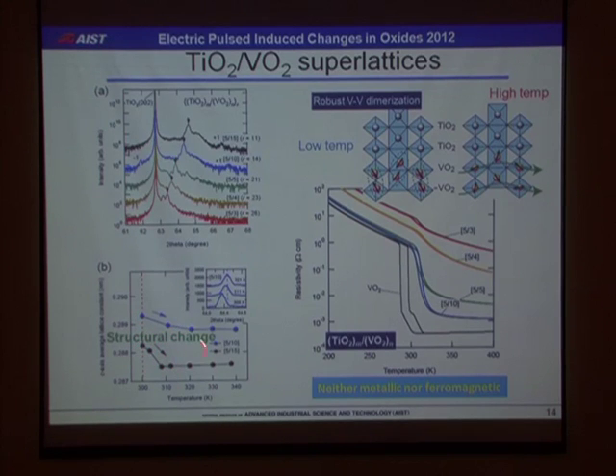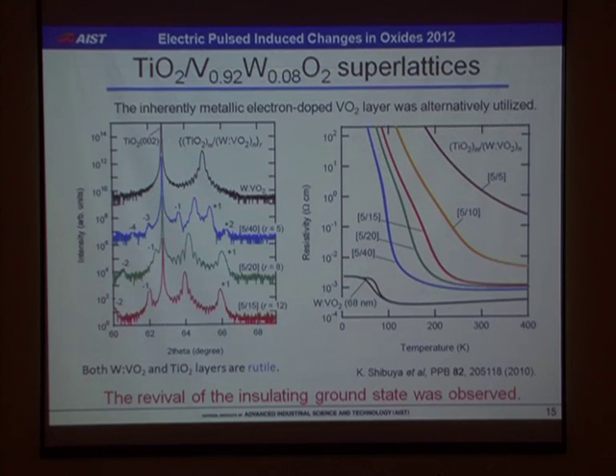This indicates the structural phase transition. And actually, the feature of dimerization was seen even when the layer thickness of VO2 is 3 unit cells. So this is due to very robust vanadium dimerization even at the interfaces. Actually, neither a metallic nor a ferromagnetic state was observed, only insulating ground states. Because we haven't observed a metallic state in the previous case, we alternatively utilized inherently metallic electron doped VO2. So we fabricated this kind of superlattice structure.